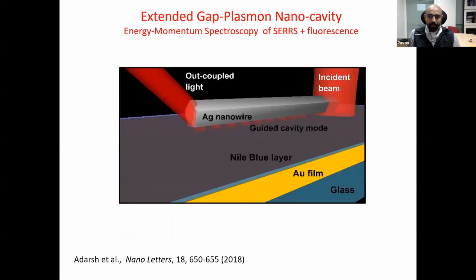Now, one of the consequences of studying such interaction is to look at what happens if you take a gold film, and you have a silver wire, and you sandwich a molecular layer between them. To begin with, for this molecular layer we have used a very well-known molecule like a Nile blue layer, but you can now also replace that with two-dimensional chalcogenides, let's say MoS2, graphene, and other such materials. What we have observed is something called an extended gap plasmon cavity. Instead of having gap plasmons only at one particular location, we can now extend this gap plasmon along the length of the wire.